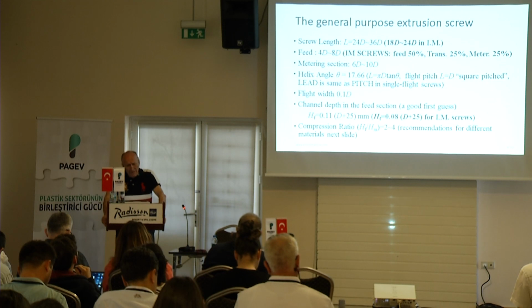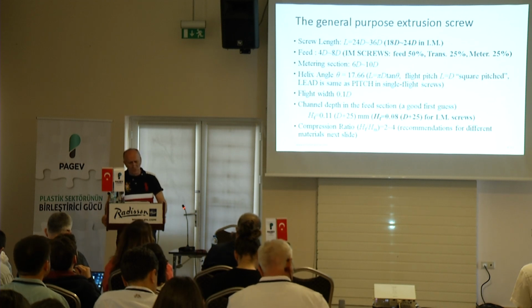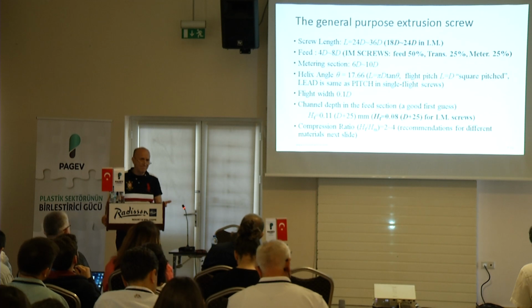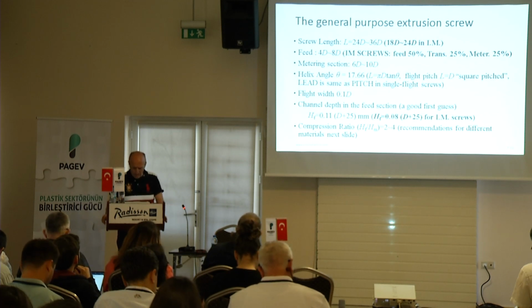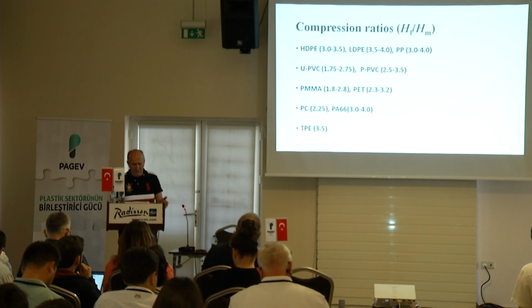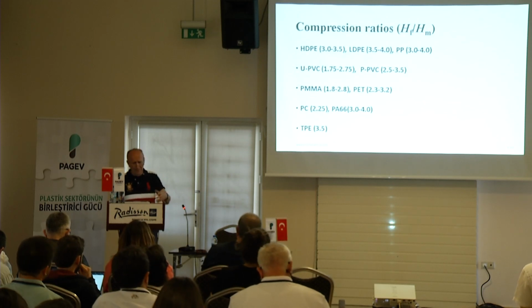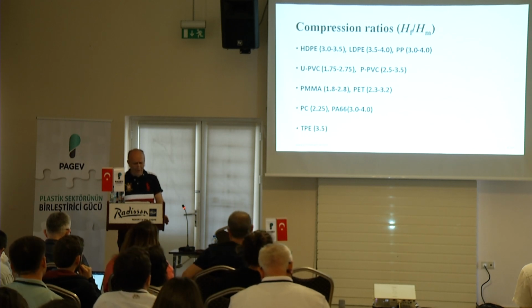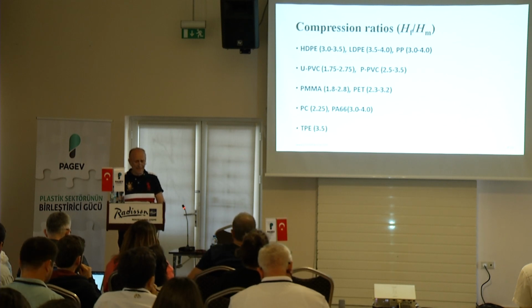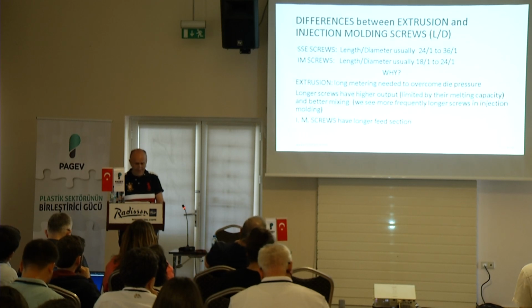After that, I'm talking about general purpose extrusion screws. I give you actual numbers, if you want to check against any particular designs. If you want to start, compression ratios for HDPE are probably 3, 3.5. Polypropylene 3 to 4. If it's something like PVC, it cannot take high compression ratios. You probably go around 2, 2.5, and there are different recommendations. There's nothing very much to say.